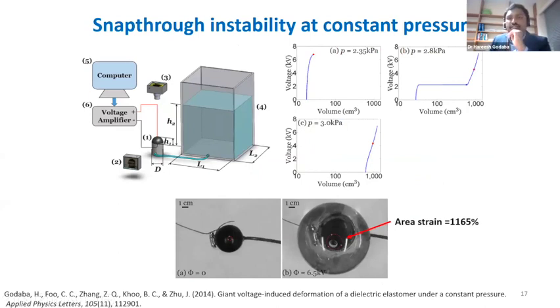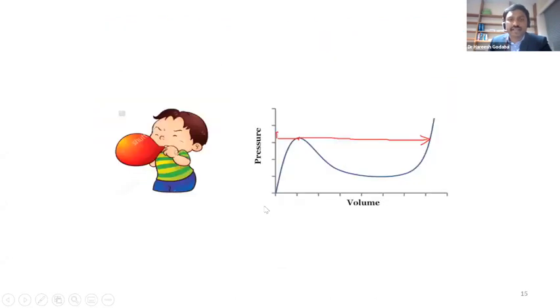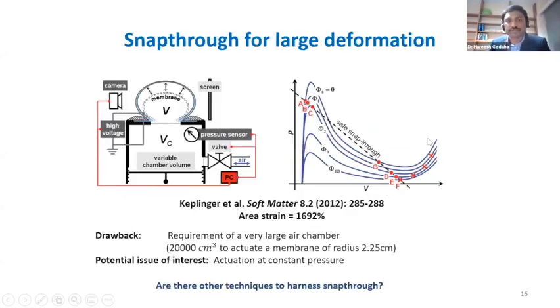we basically looked to see if there are other methods through which we can achieve snap through. And what we figured is that in this PV curve that we see, if you put the membrane very, very close to the verge of instability, which is very close to the top of this N-shaped curve, then we can actually use a very small voltage to trigger this snap through and end up on this other side of the curve, which gives us very large volume change.